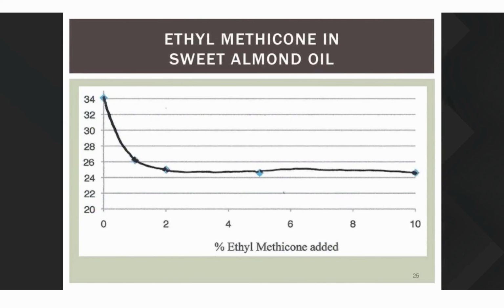Okay, and in a typical example, we have a product here where it's ethyl methicone, which is added to sweet almond oil, and you can see the numbers are much lower. We have some things that are less than 0.5% that lower surface tension. Now, the interesting thing is these polymers can lower surface tension and alter rheology or give a powdery feel, so we have to pick the right one.